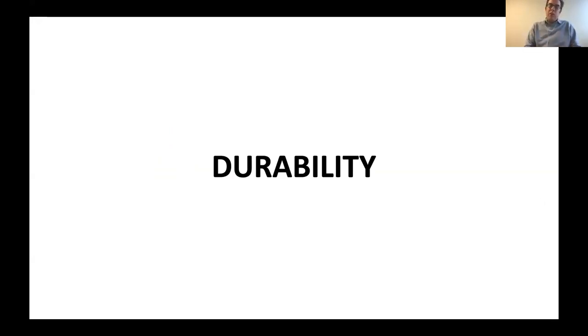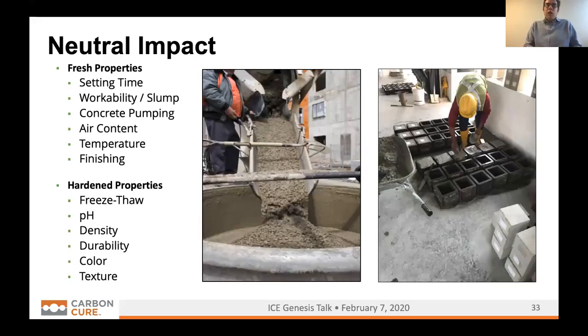If we're providing concrete into the broader market, we have to make sure that it both performs as necessary and is sufficiently durable and lasting. So in our testing, we have established, not only to ourselves but our producers have established through their own quality control data, that we're not doing anything unacceptable by adding this CO2. Nothing unacceptable happens to the setting time. Nothing wrong happens to the workability or the slump. You can pump the concrete as you always did. The air content is where you need it to be. You haven't made the concrete warmer or colder. And the concrete can be adequately finished by the people who have to work in flat work type situations.